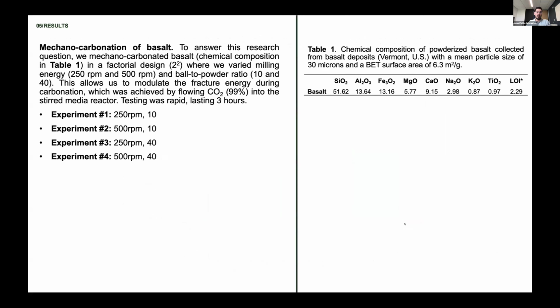So just to give you an idea of the experimental setup. The first thing is we are exploring 4 different conditions, 4 different experiments, where we are mechanocarbonating this basalt. The chemical composition of the basalt, I want to just point out, is in table 1. What you can see is that we have 5.7, almost 5.8, weight percent of magnesium and about 9% by weight of calcium. Those are the 2 main components that we're trying to carbonate, that we're trying to use to convert CO2 gas into a mineral.